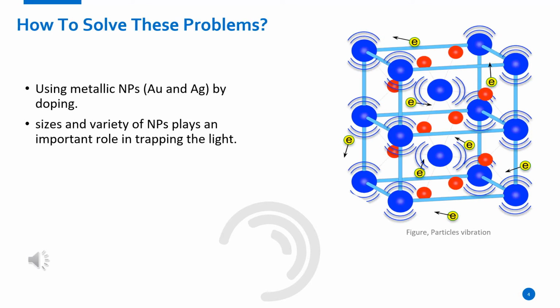We tend to solve these problems using metallic nanoparticles. Doping techniques are used for gold and silver nanoparticles to put them on the surface of the organic solar cell. The difference in size and variety of nanoparticles play an important role in trapping the light. So, when the light is sent to the metallic nanoparticles, the energy of the light is stored in the vibration mode of the nanoparticle as a result of scattering and absorption of the light. So, this will improve the efficiency of the device.